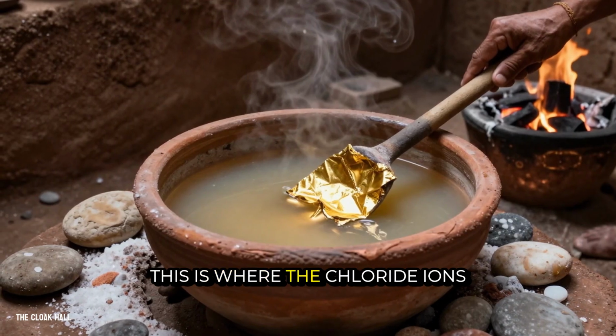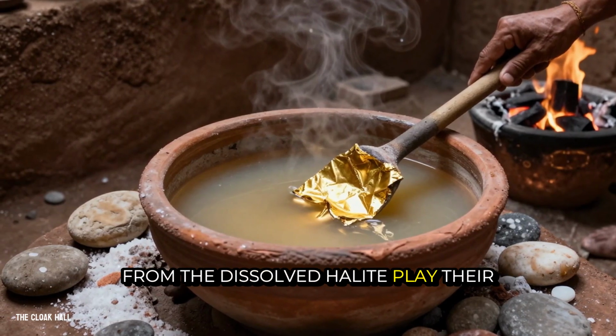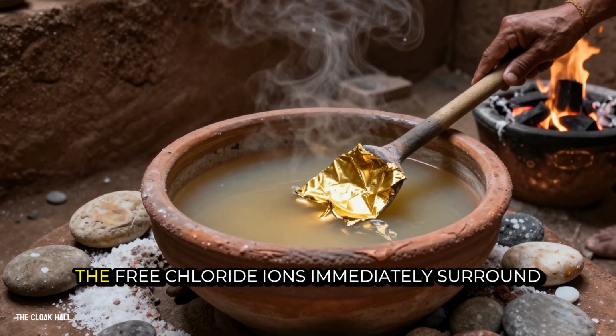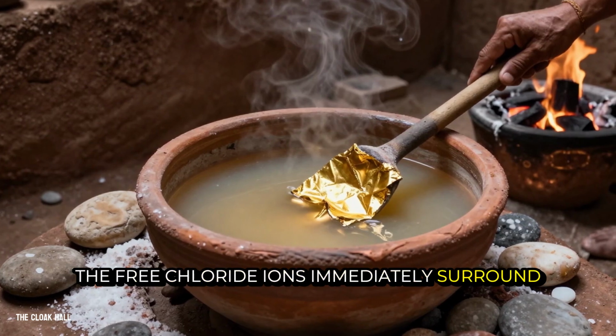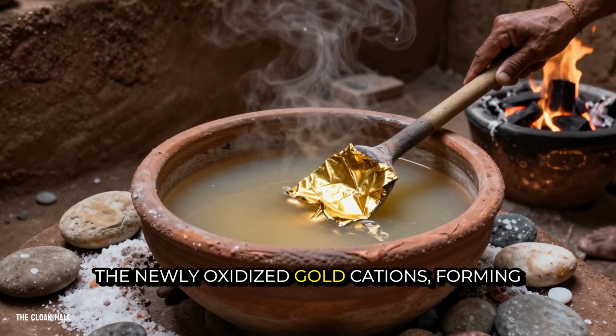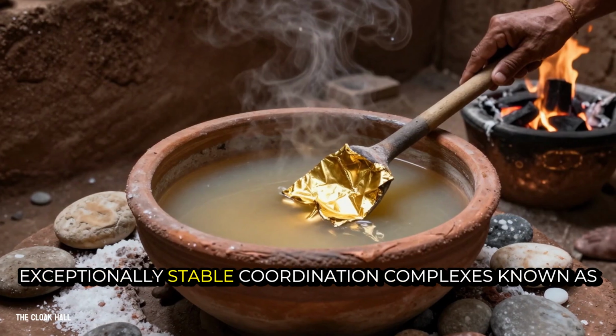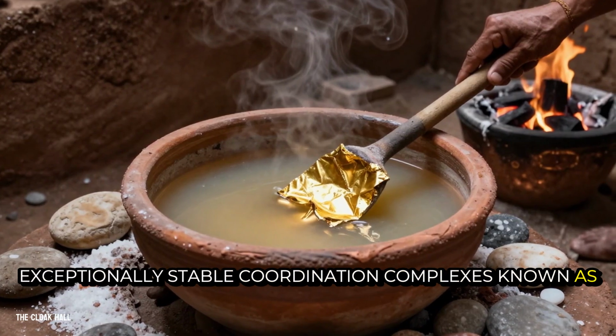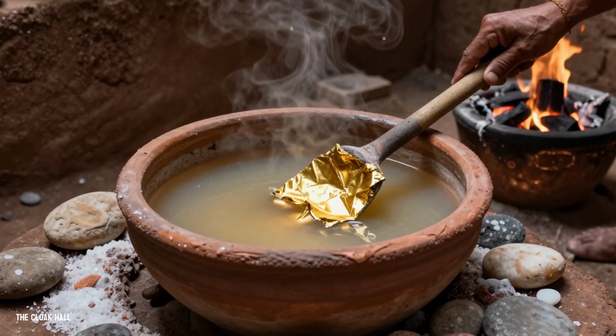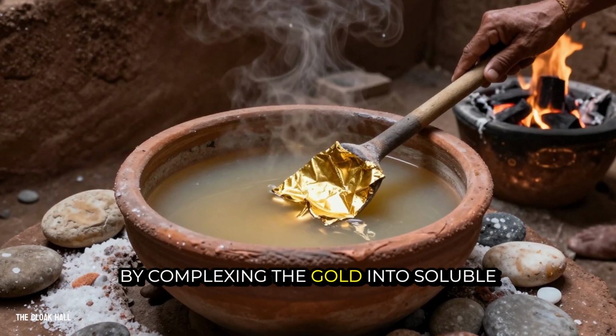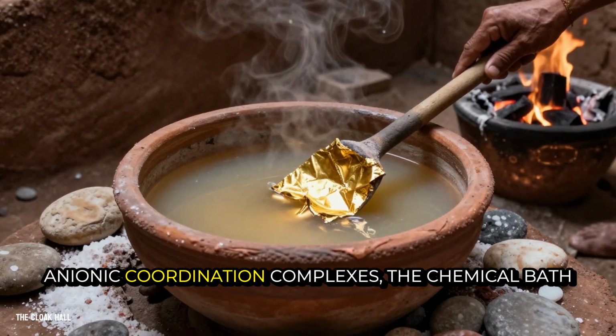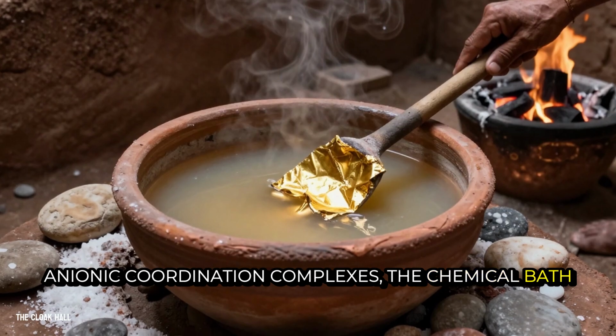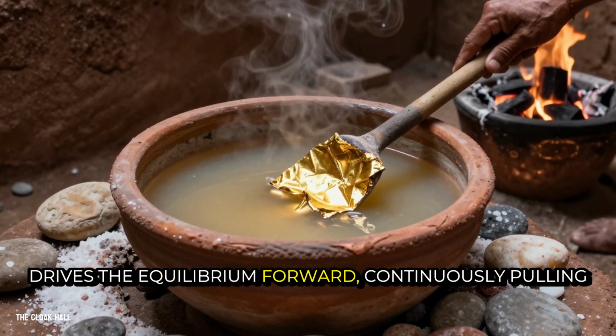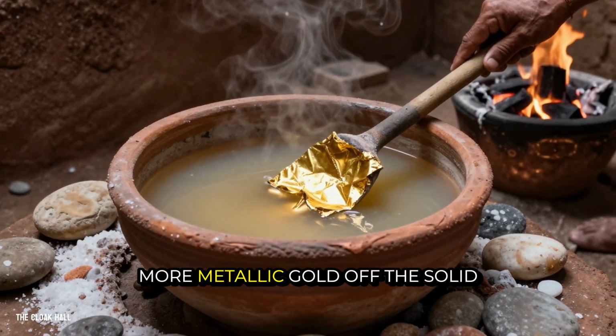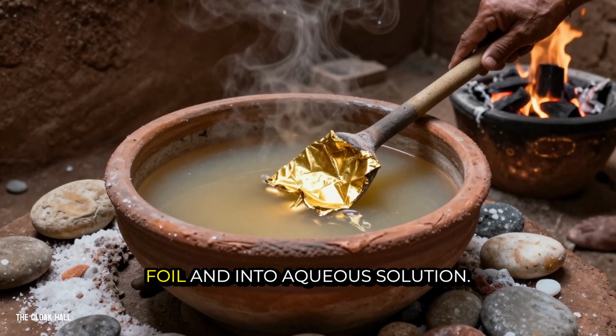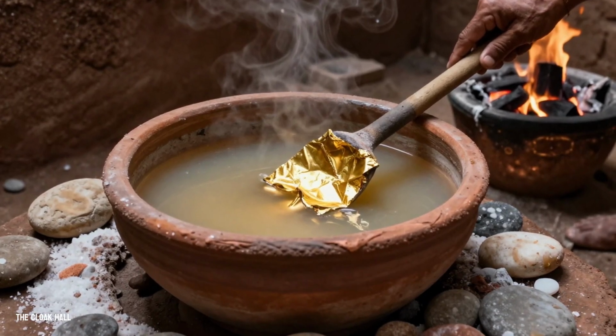This is where the chloride ions from the dissolved halite play their decisive role. The free chloride ions immediately surround the newly oxidized gold cations, forming exceptionally stable coordination complexes known as tetrachloroaurate ions. By complexing the gold into soluble anionic coordination complexes, the chemical bath drives the equilibrium forward, continuously pulling more metallic gold off the solid foil and into aqueous solution.